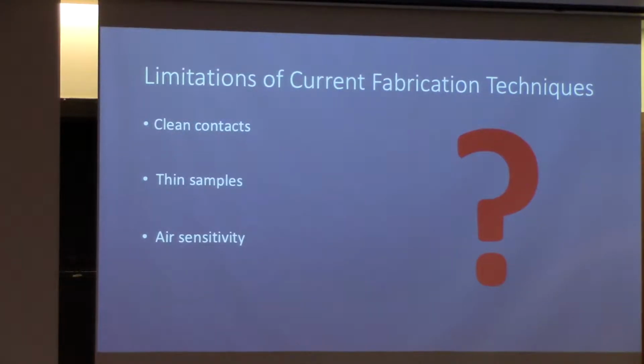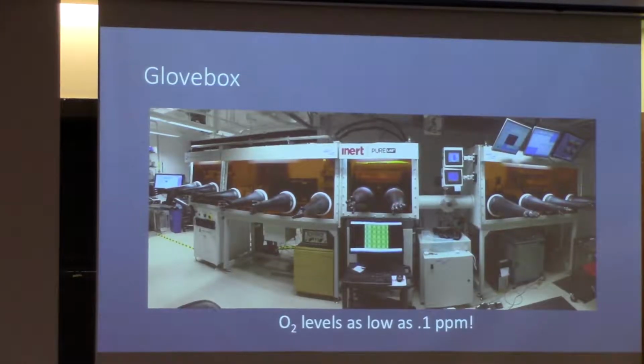So in order to solve the challenges of cleanliness and air sensitivity, in the Birch lab, we do all our fabrication inside this lovely glove box. It's full of an argon atmosphere, which is inert, and contains almost no oxygen, levels as low as 0.1 parts per million. So I can do the entire fabrication process, make an entire device without my MoTe2 ever seeing air.